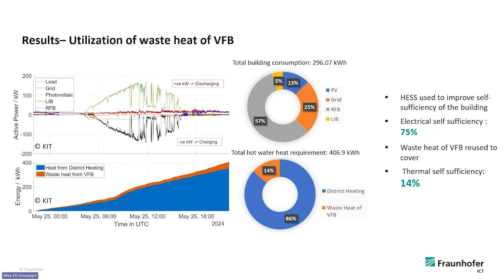There are some other losses which are due to osmotic losses in the battery, but mostly it is actually heat. So one idea was to gain more efficiency in the system by also applying the waste heat. And it could be shown in the coupling module that 14% of the waste heat could be utilized by the battery itself. So with this coupling module, the big surplus of energy, especially from the solar plant, could be utilized for heating. So they got a self-sufficiency rate of 75% and a thermal self-sufficiency of 14%.